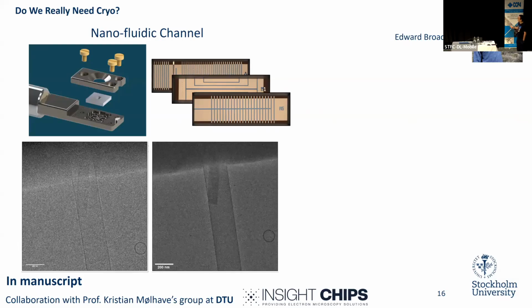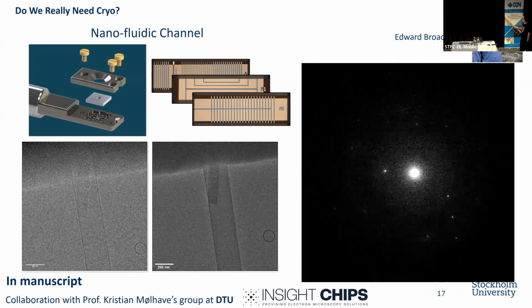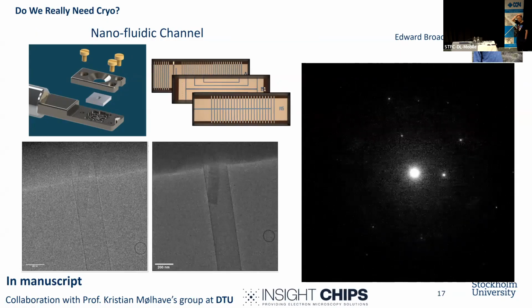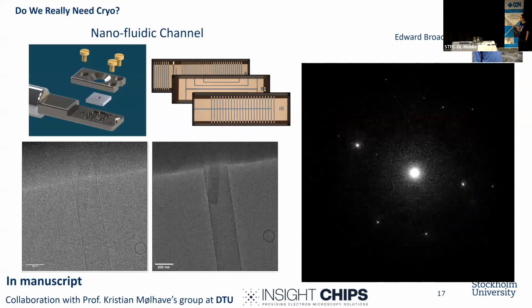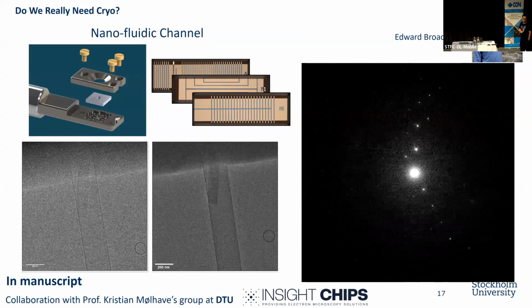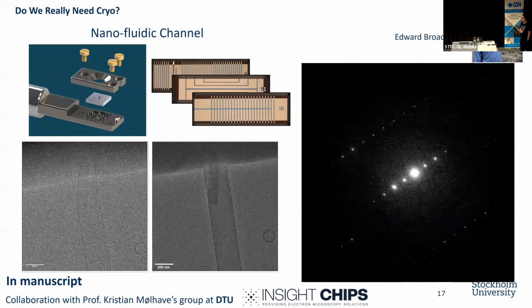So this is not a protein crystal yet, it's a small organic molecule. We actually were able to grow this crystal inside the channel. So this channel is very, very small, 200 nanometers in width. And here is the crystal grown without any liquid. And then when we fill the liquid, you can see the contrast difference. And we were able to collect very nice MicroED data. We got slightly higher background, but the data quality is quite nice, and we could solve the structure relatively easily.